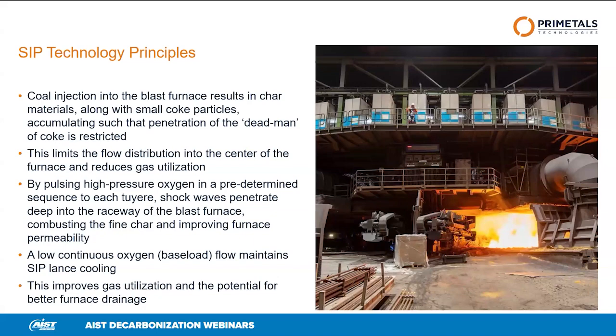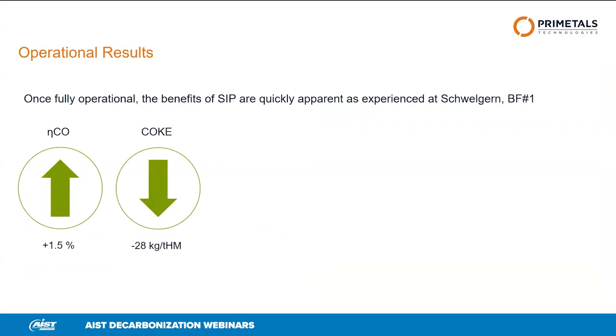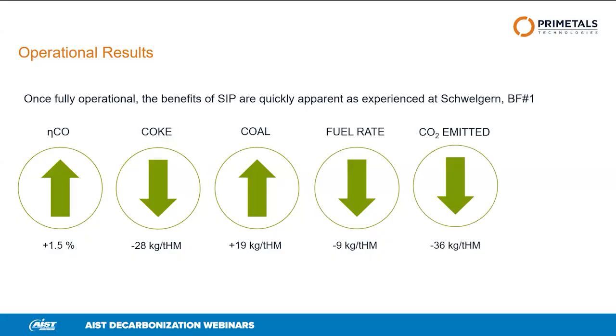Picture of the plant at Schwelgern, and as you can see, the top of the picture there is a pulsing box for each tuyere. What does it mean? This is what was seen at Schwelgern. As I said, ETA-CO, the efficiency of carbon utilization up, coke significantly down, coal up, fuel rate down, CO2 down. Again, an incremental CO2 reduction, but the coke saving, where coke is your most expensive fuel, can and does lead to return on investment of maybe 2 years for a project. And Primetals are currently building the first SIP plant outside of Germany in India on a 5,000 cubic meter blast furnace.